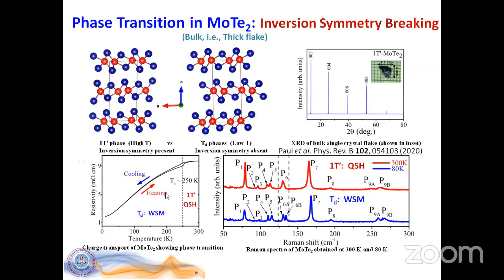And then we recorded the Raman spectrum across this temperature, the phase transition, and we could see that the high temperature phase, which relates to the T prime phase, that is the monoclinic phase, has the inversion symmetry. So there we have this typical Raman spectrum where one can see, we have just labeled them from P1 to P9. But once it goes to the low temperature phase, which is the Td phase, and also happens to be the Weyl semi-metallic phase, there we see an additional peak coming up, which is right over here. And that's the signature in Raman of the structural phase transition.